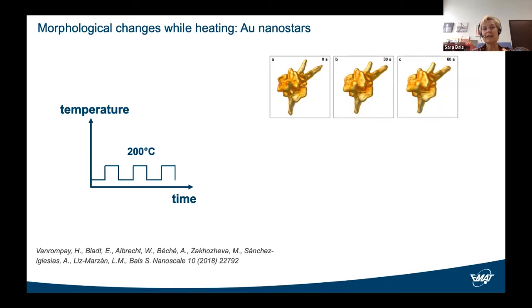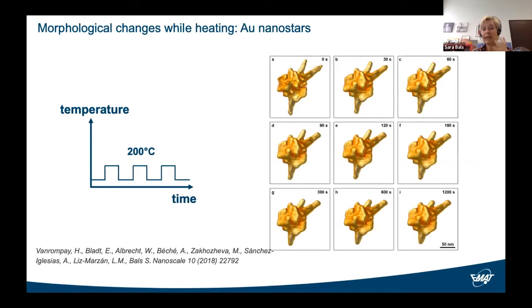And because these tilt series can now be acquired in 5 minutes or so, we can keep on repeating the process and we can acquire a whole lot of these tilt series and we can actually sample what is happening as a function of heating time. What is happening is very clear. The sharp tips will become blunt and that will definitely influence their properties.